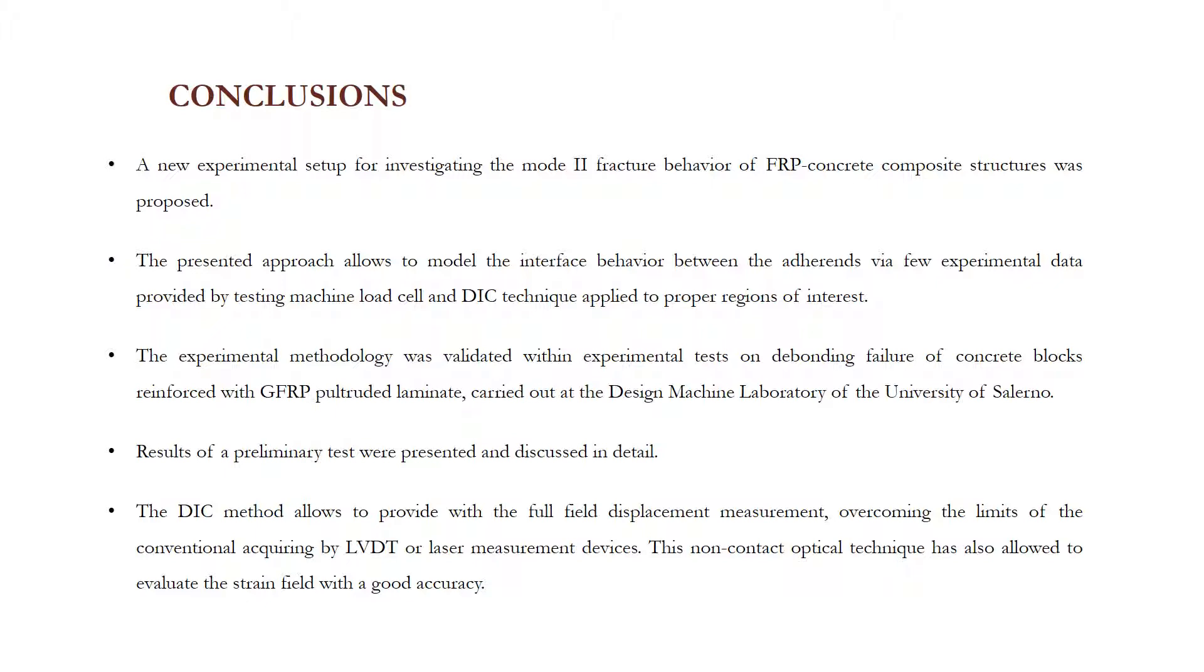A new experimental setup for investigating the mode-II fracture behavior of FRP concrete composite structures was proposed in this paper. The presented approach allows modeling the interface behavior between the adherends via experimental data provided by testing machine load cell and DIC technique applied to proper regions of interest.